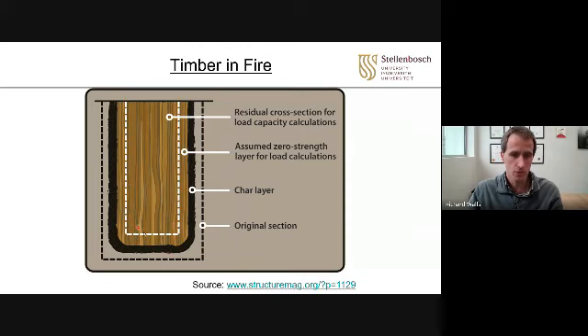You use your residual cross section, and as long as the residual cross section is fine, then you can design for it. So what you want to make sure is that the beam is big enough, even after a 1 hour or 2 hour fire, it's still sufficient. And you can put products on. So let's say the timber is too expensive, you can clad it. You can put an intumescent coating on it. There are various things that you can do to try protect the timber and get to a result.